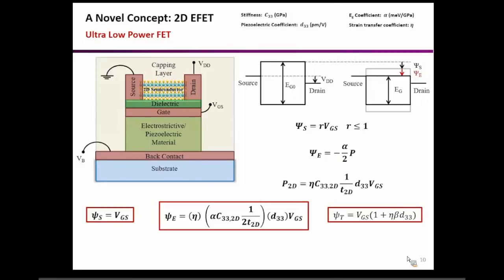So what really happens is that when you apply a normal gate bias to this 2D material, in a normal transistor you will just move the bands, right? And this band movement is generally given by the surface potential, and the surface potential is generally close to the applied VGS. In the ideal case, this quantity R could be 1 when you have a very clean interface, and also a better electrostatic control by a high-K dielectric. So this R could at best be 1, but not more than that. And that is the limitation which doesn't allow you to go beyond 60 millivolts per decade.